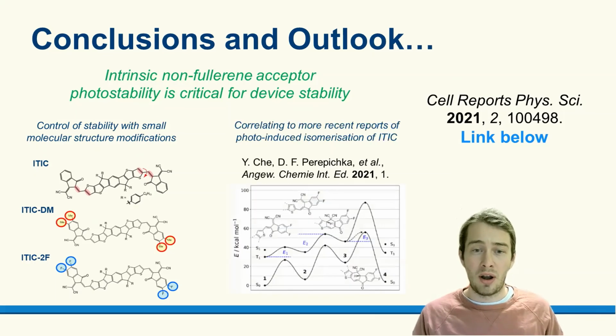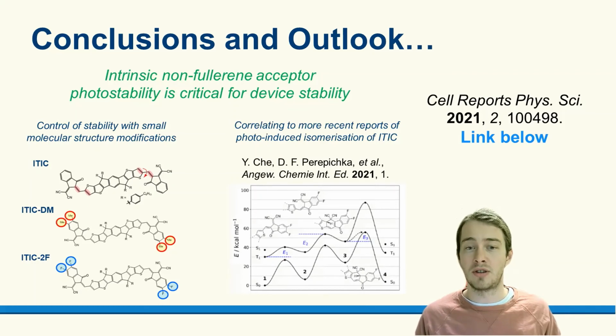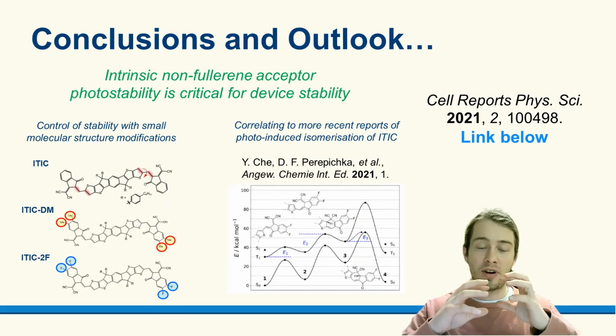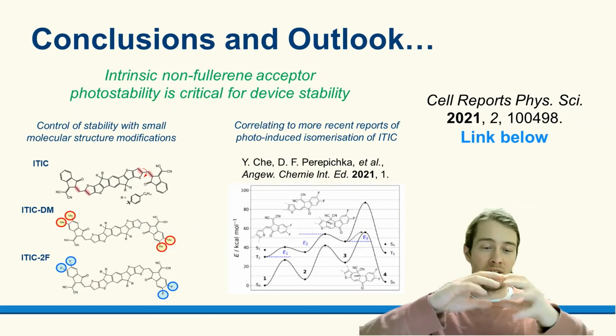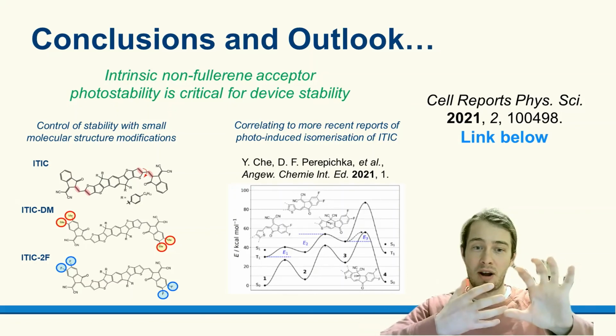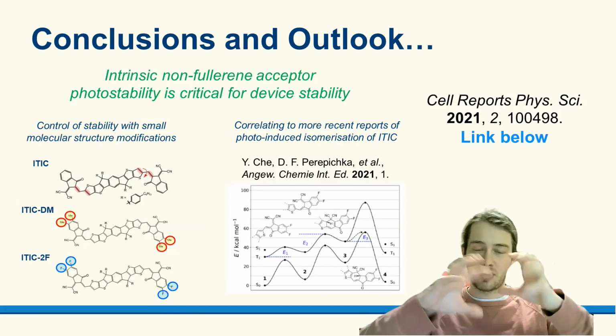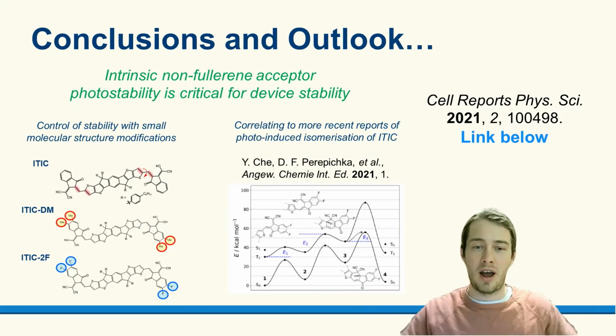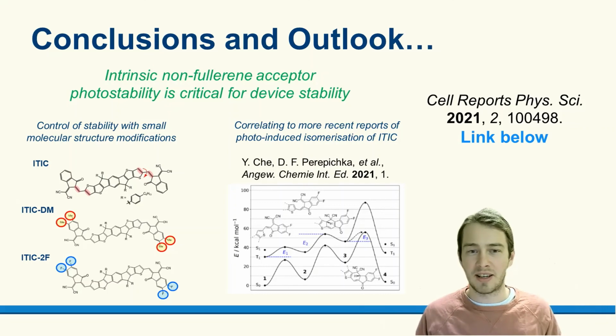We also want to see how our results correlate to more recent reports on the photo-induced isomerization of ITIC, which is shown to be a degradation process, and you can follow the reference if you want more details on that. And this is fairly consistent with our reports of a conformational change. For there to be an isomerization, there first has to be a conformational change, then a cis-trans isomerization, and so all this requires quite a lot of molecular motion. And so we think this is fairly consistent with what we found as well.